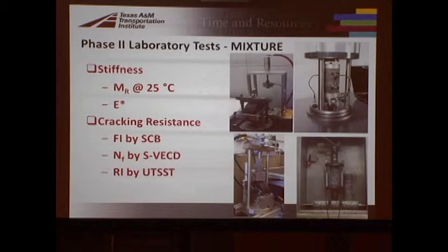And for mixture, we're looking at stiffness in terms of resilient modulus at 25C, because it's easy and cheap and repeatable. And on the same specimens that we do resilient modulus, we're able to run the semicircular bend test and get something called the flexibility index. So we're able to get an intermediate temperature cracking resistance of the mixture.